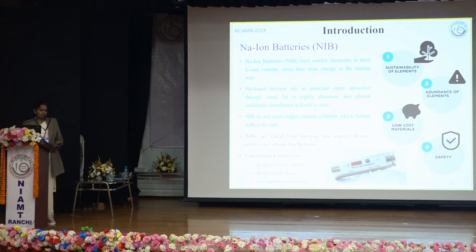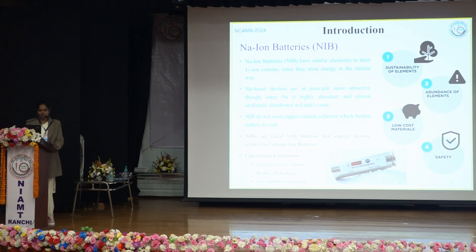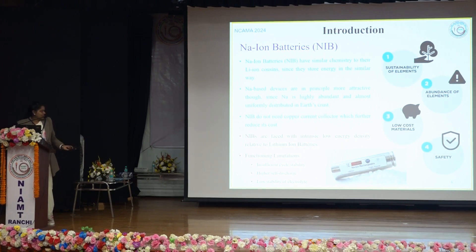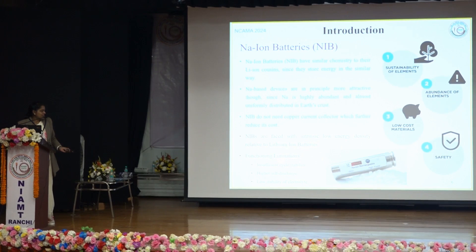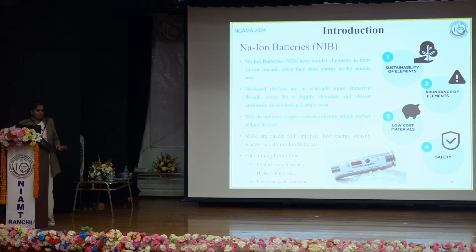Sodium ion batteries are similar to their lithium ion cousins since they both store energy in a similar way, but sodium ion battery-based devices are in principle more attractive because of advantages like sustainability, abundance of elements, low cost, and safety. However, sodium ion batteries face issues like intrinsically low energy density compared to lithium ion batteries, insufficient cycle stability, higher self-discharge, and low stability of the electrolyte.